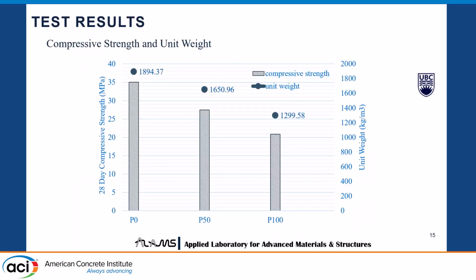So if we look at the test results, if we look at the compressive strength, so P0, P50, and P100. P0 gave us a compressive strength of 35 MPa. With P50, we got around 27.5 MPa, and with P100, we got around 21 MPa. So we can see the strength is gradually decreasing with the addition of poraver.